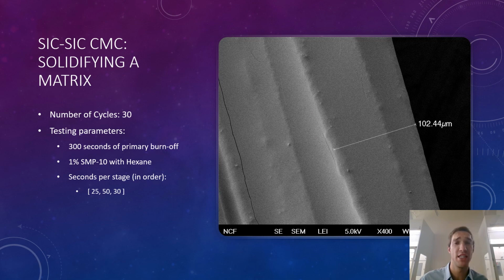Here we're looking at 30 cycles. This image has the 300 seconds of primary burn-off, which the previous slide did not. Again, I'll get to that in a second. But this one, as you can see, is a really significant matrix buildup. Again, that has good adhesion without any cracking or bubbling. You can see a few small cracks, but again, those can get filled in by subsequent infiltrations. And then we're going to move on. This is a good result. It's really solidifying a pretty significant matrix here.